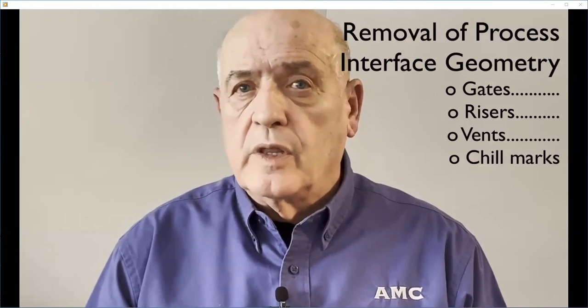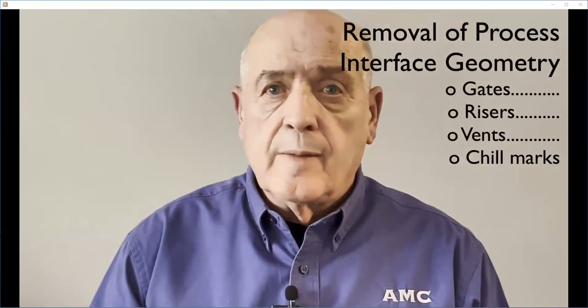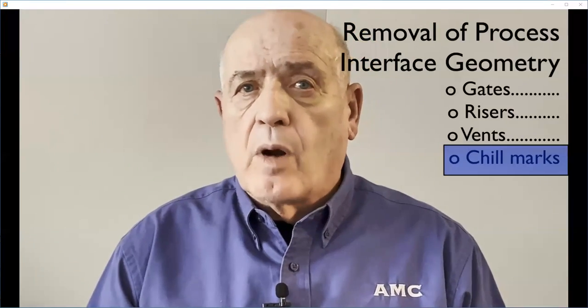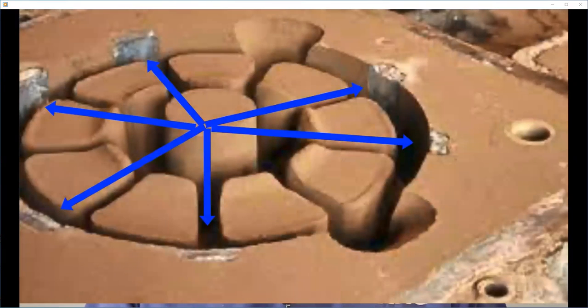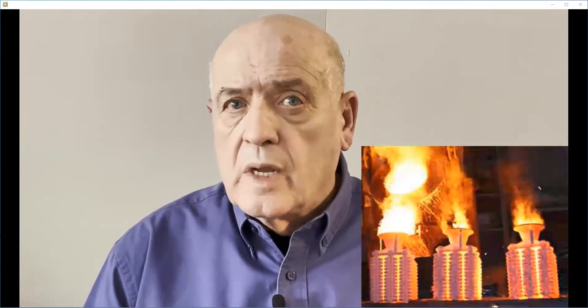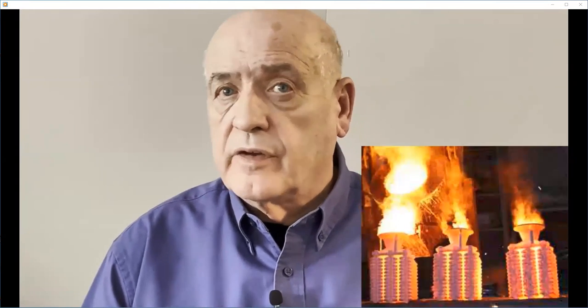Before moving on to the finishing processes that assure specified solidification integrity, let's define the difference between the fourth kind of process interface geometry and the other three. That fourth kind is markers from the placement of metal chills in the mold walls of sand castings. High specification air-set sand castings in aluminum, magnesium, and lightweight steel castings especially use chills to accomplish the specified solidification integrity and the resulting mechanical properties. Because investment castings are poured in a preheated, very hot ceramic shell mold, chills are not involved in setting up solidification integrity.